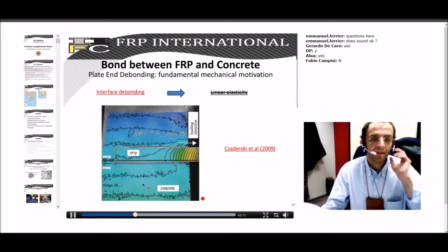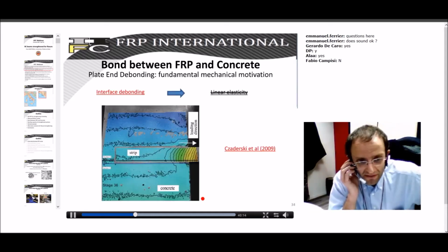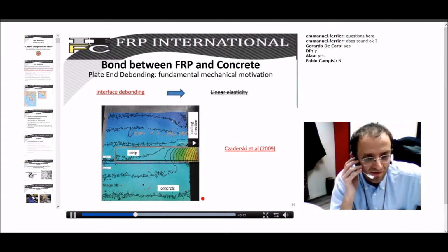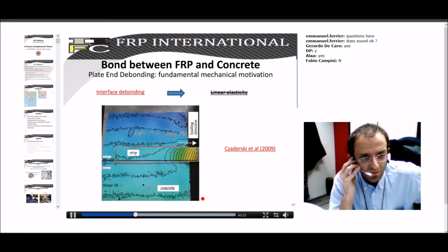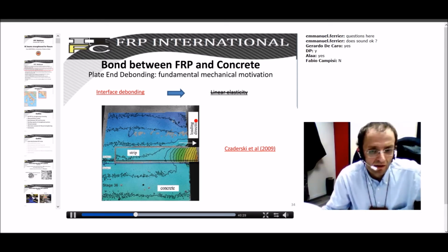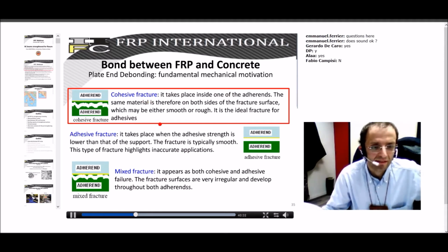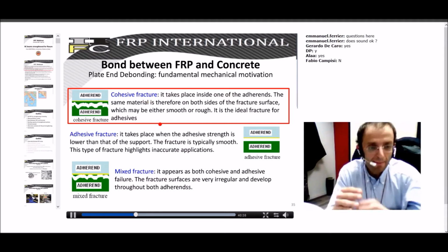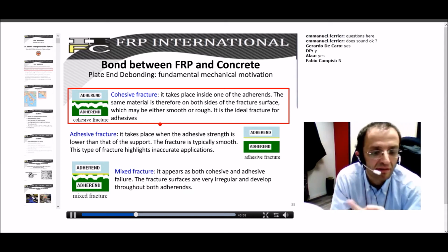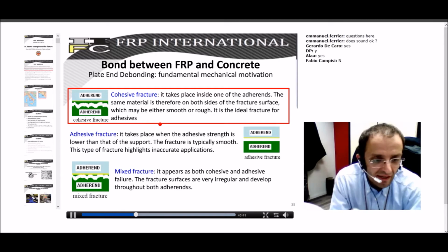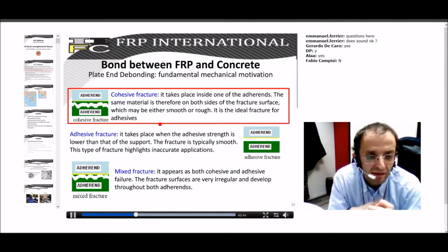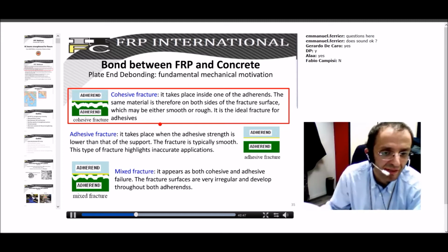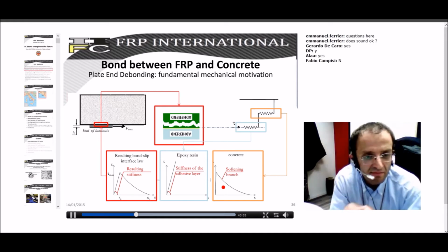the interface is not actually linear, because when a certain level of stress is attained, some cracking phenomena develop in the interface just beneath the adhesive layer. So you can probably see that there is a cohesive fracture developing in one of the two adherends. Typically, it develops in concrete. Other kinds of fracture can theoretically develop, even though the cohesive fracture is the most common in FRP strengthened RC beams, and this is a mechanical justification of this.